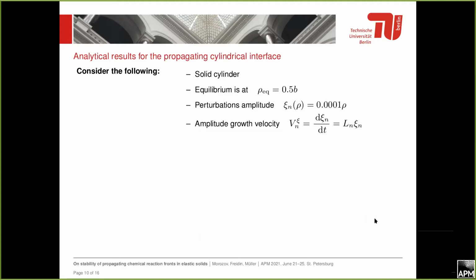And as mentioned recently, we're working on a paper right now, all these results are relevant not only at the equilibrium position, but also at the propagating interface. So basically, we are linearizing our kinetic equation not at the point of chemical or thermodynamic equilibrium, but on the moving interface. And to understand how the velocity of the amplitude change or growth and the velocity of the propagating interface are related, we should consider the following. For example, we consider the solid cylinder, and we consider the configuration at which the equilibrium is in the middle of the cylinder, so the equilibrium radius is 0.5.